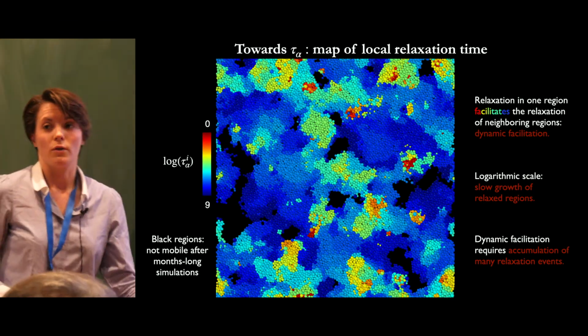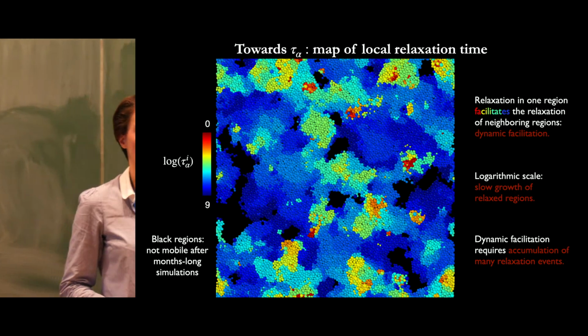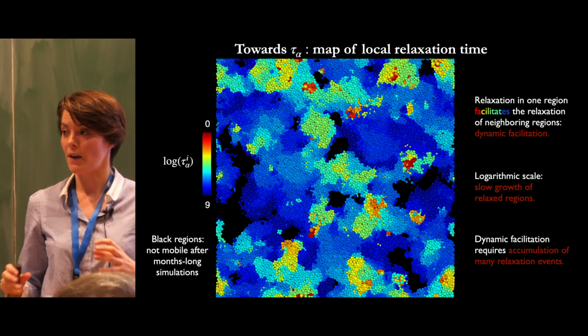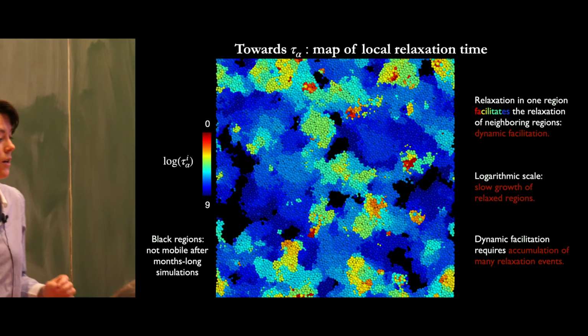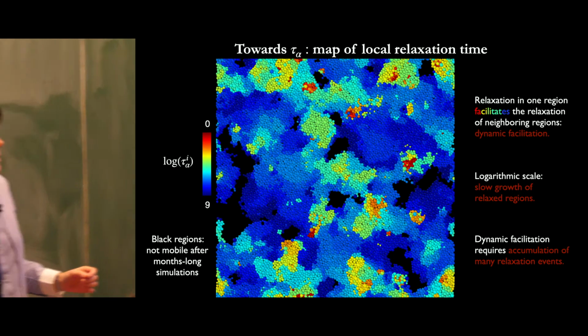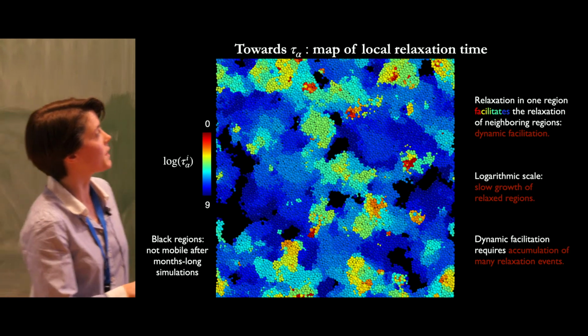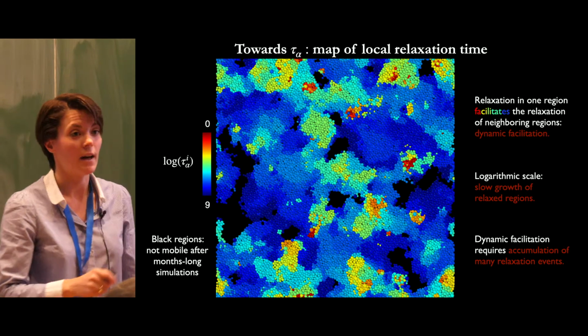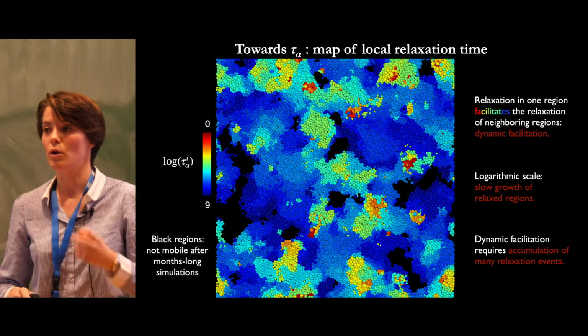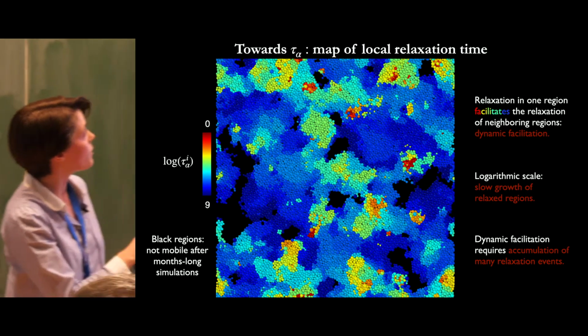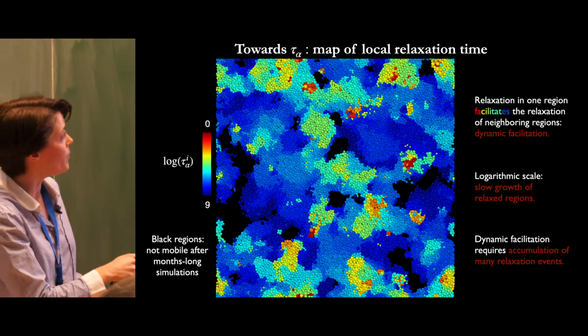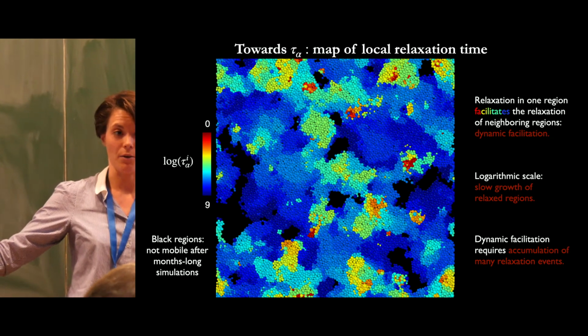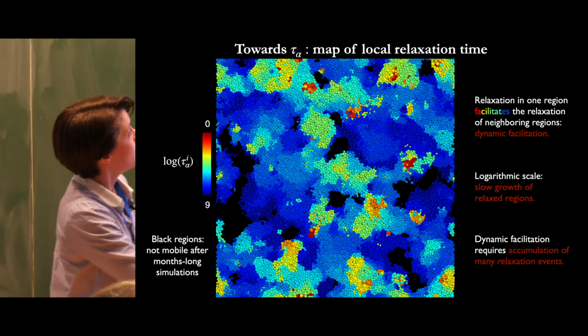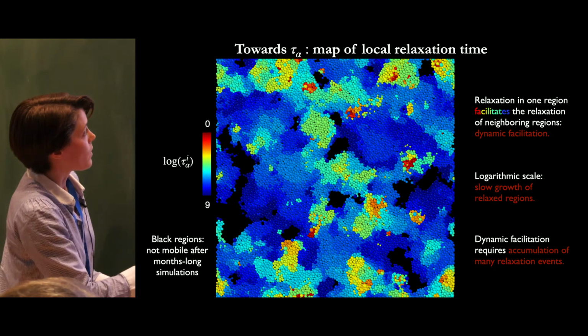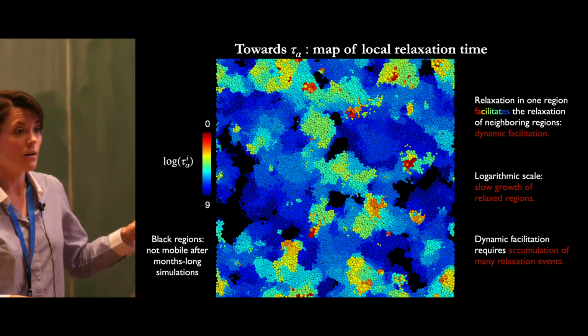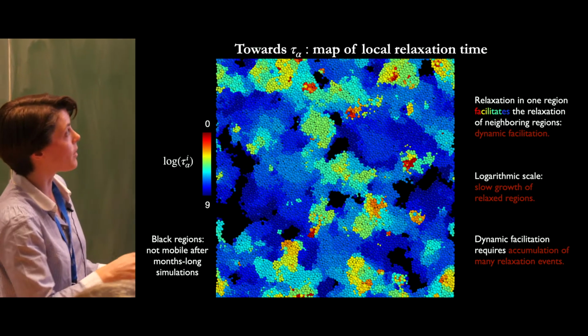Now moving from short times to longer times, I showed you in the movie that there is a clear structure in space and in time as to how the dynamics proceeds, starting from these initial clusters. Here I'm showing the same configuration, but now I'm plotting the particles with a color that codes for the time at which they lost half of their neighbors, their local relaxation time. It goes from red at very early times to dark blue, which corresponds to 9 decades in time later, a really huge separation in time scales. The clusters that I discussed correspond to these red regions. Here you see that they're really rare and a priori far apart initially.